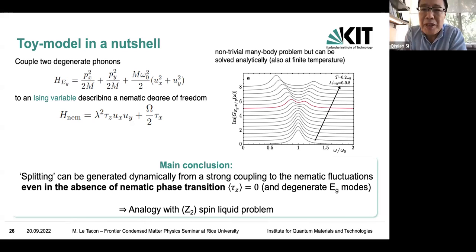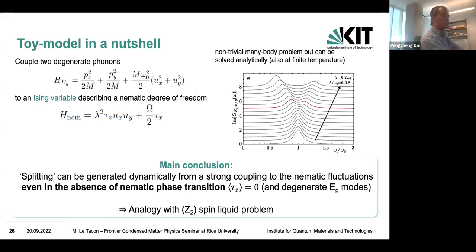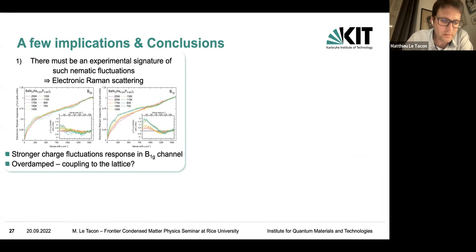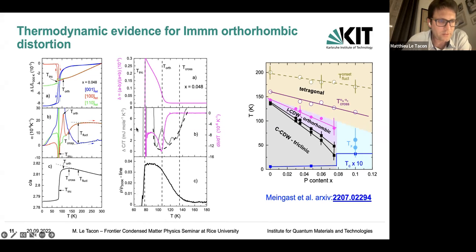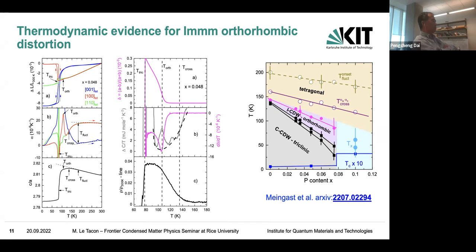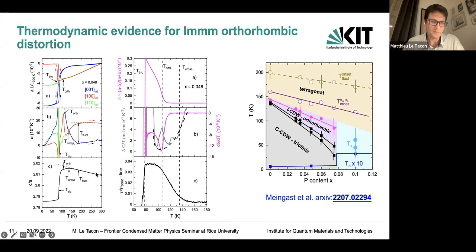Well, maybe you should finish your train of thought. No, I was just saying, for temperatures well above the orthorhombic phase transition, there's no other thermodynamic measure. What you have above is something weird going on along the C-axis. If you look here at the C/A ratio, it is increasing. That means that as you cool, both A and C contract, but A seems to contract a bit faster than C. This is an anomaly on its own.